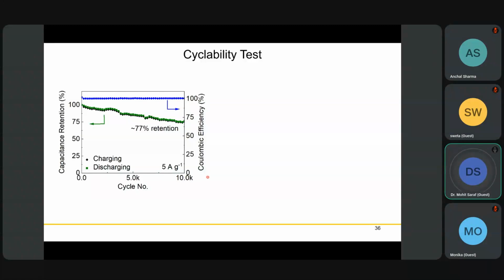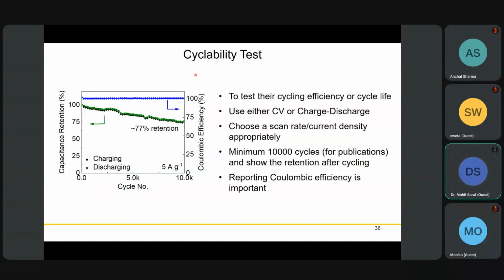This Coulombic efficiency is shown by the blue curve, and it remains nearly 100% throughout the 10,000 cycles, so it is very important. This axis belongs to capacitance, and this axis belongs to Coulombic efficiency, so it is important to mention it. You can use either CV or any charge discharge technique for the cyclability test, and then choose a scan rate and current density wisely, where you can observe all the features of your electrode and electrolyte interface.